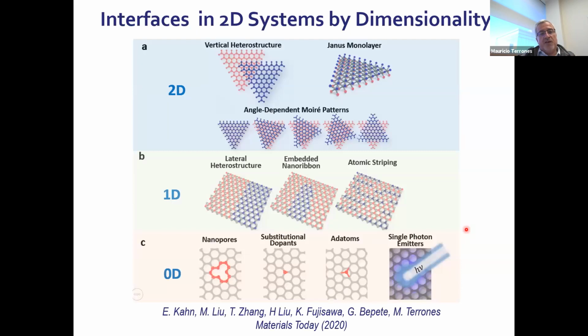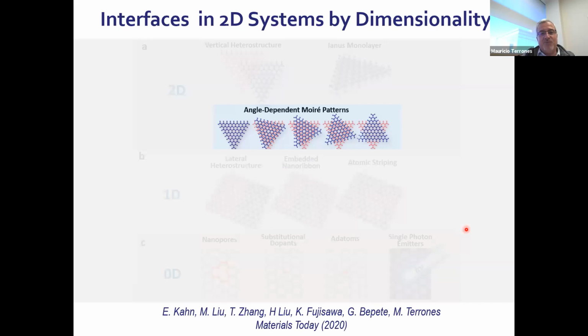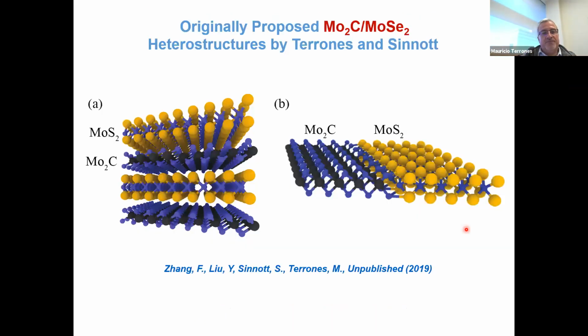So let's try to have some, well, I call these moiré patterns, but you will see why I'm calling this moiré. Because when you have 2 hexagonal lattices, or 2 periodic lattices, when you start twisting them, you start to have interesting patterns. And with 2 hexagonal ones, you have this moiré. So one thing that we tried to do, and we submitted a proposal that I thought was impossible, we said, okay, let's try to make some hetero interfaces of moly carbide and moly sulfide, although moly carbide is a bulk material, it's not a layered material, and moly sulfide is a layered material. So can you make these hetero interfaces, or vertical ones, that was something that we were wondering, but the way to do it is you can use a templated method.